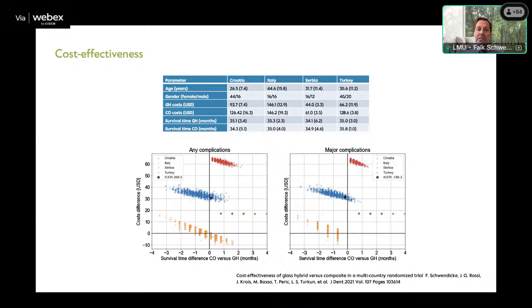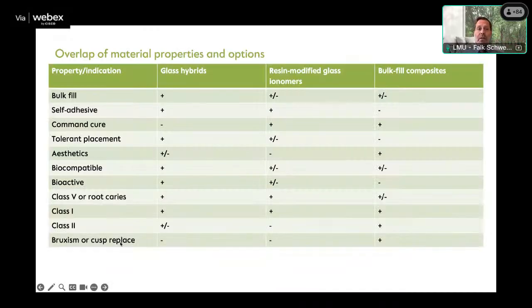And we conducted some years ago a cost effectiveness study comparing in these 4 different countries, Croatia, Italy, Serbia, and Turkey, the cost effectiveness of a glass-based material based on that randomized trial and the composites. And you can clearly see that, if I want to highlight this here, in nearly all of these 4 centers, the glass hybrid material came with significantly lower cost and very similar effectiveness compared with the composite, which of course is a huge argument if we talk about amalgam replacement, because cost was always one of the big pros of dental amalgam.